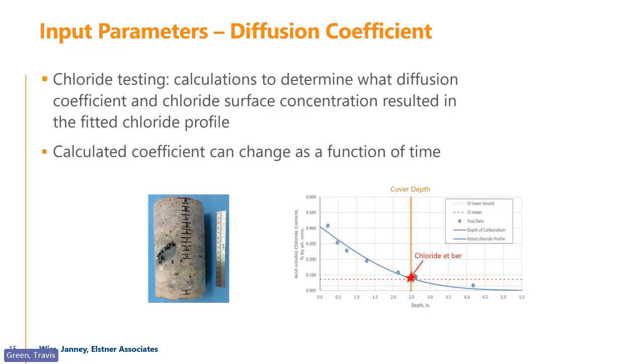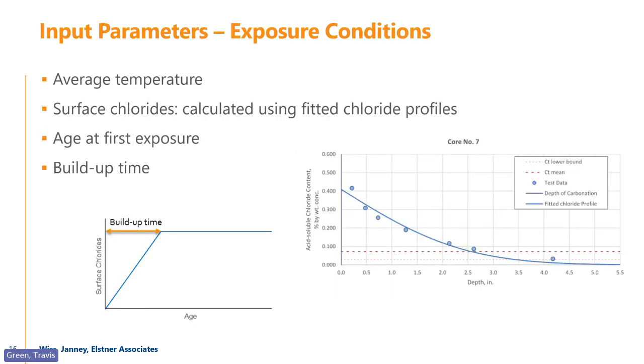We do acid soluble chloride testing, and then we curve fit chloride profiles to back calculate surface exposure and diffusion coefficient. So that's how we get that data. Then there's also the average temperature, which matters. Surface chlorides, like I said, are back calculated.